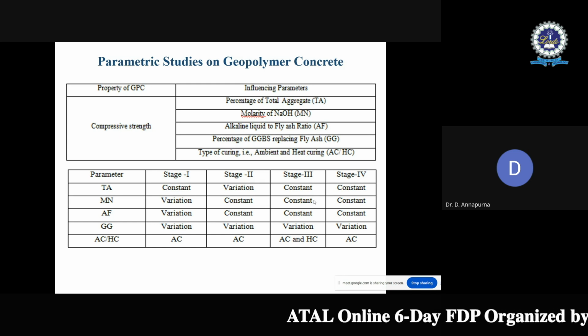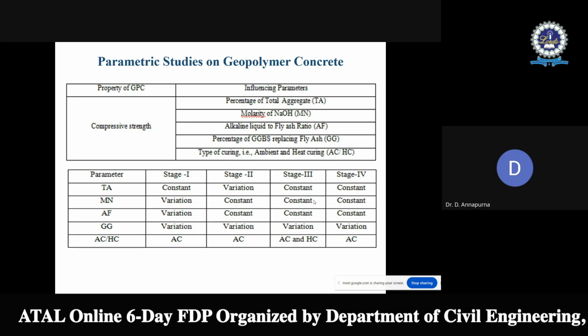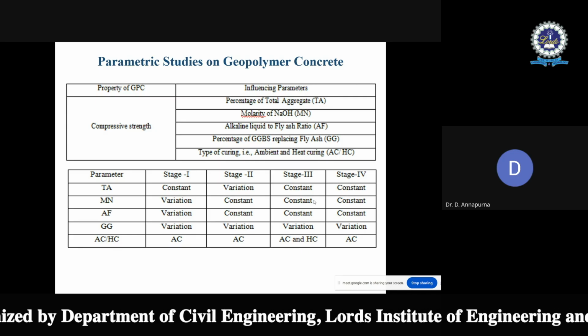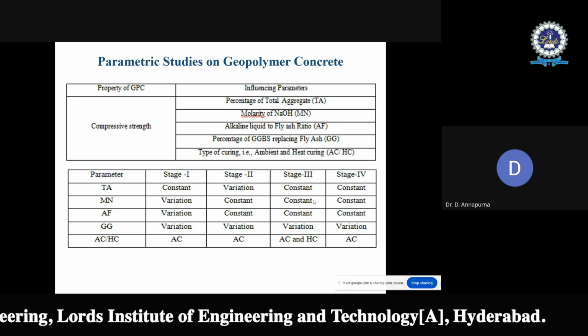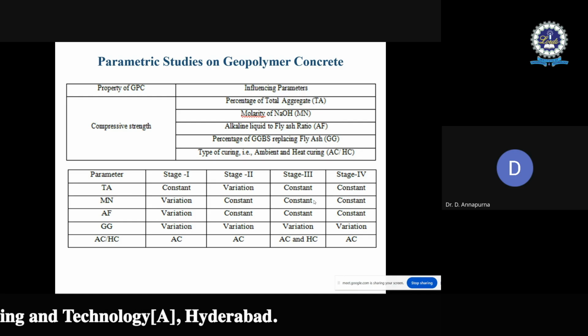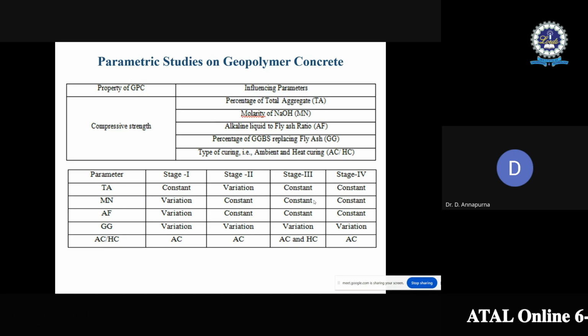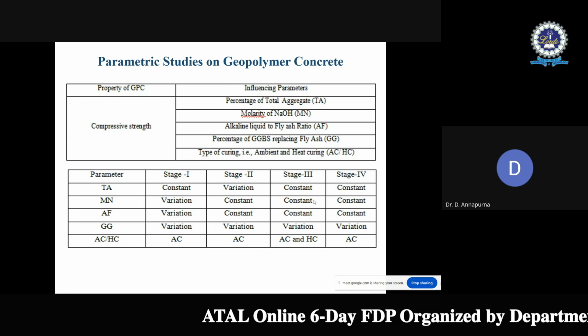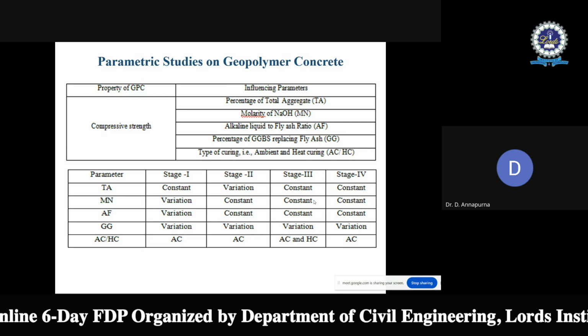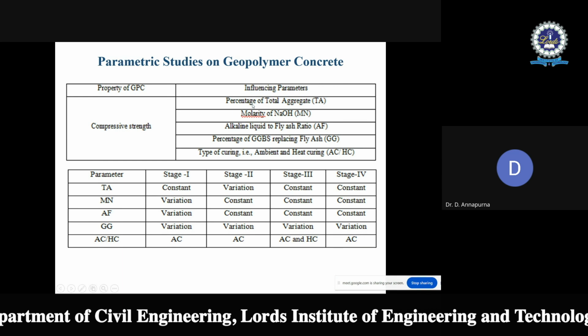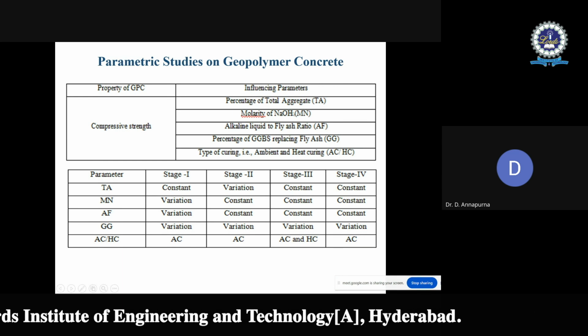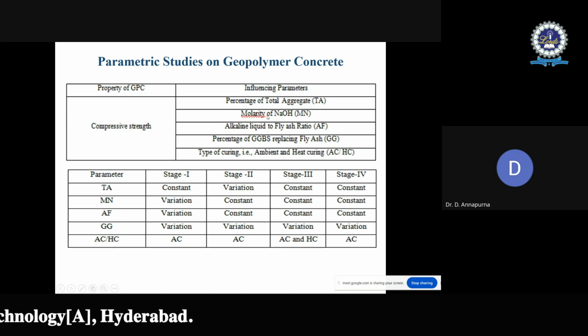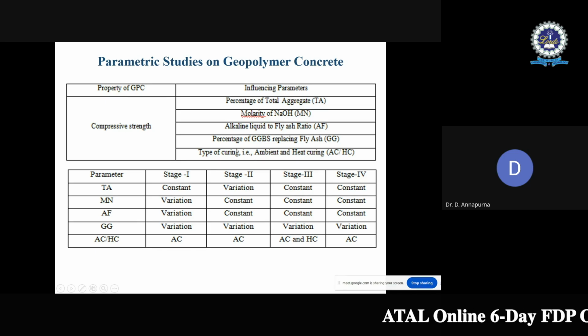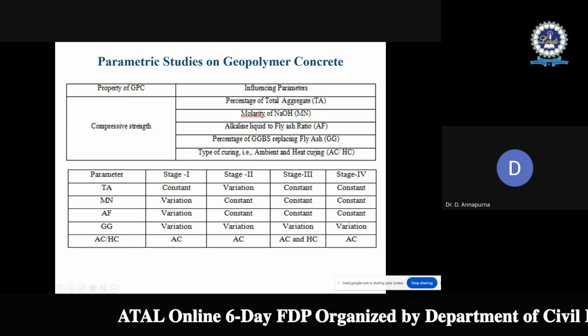This problem all the researchers might have faced, because the guidelines given by Rangan are based on their climatic conditions, material proportions, etc. In India, if you try, most of the results are not matching. So as there are no standard guidelines available on proportioning of geopolymer concrete mixtures, parametric studies have been planned as part of the first phase of this particular work. Here the influencing parameters considered are the percentage of total aggregate, molarity of NaOH, alkaline liquid to fly ash ratio, percentage of GGBS replacing fly ash. Then the curing conditions, ambient and heat curing conditions are considered.